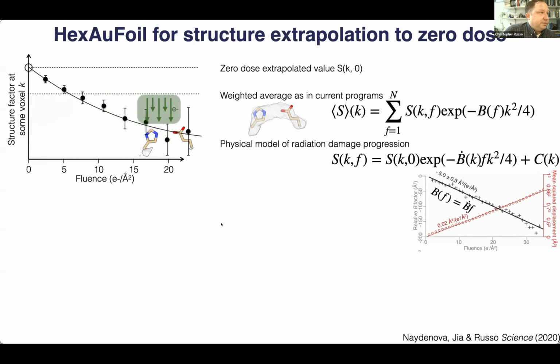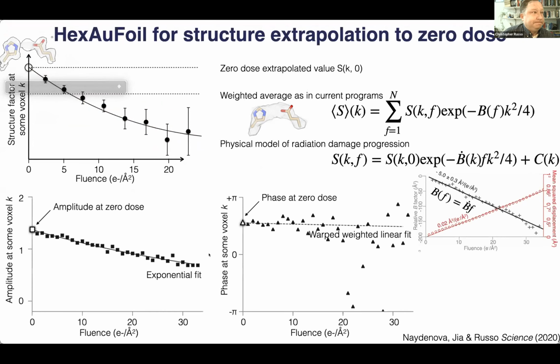So, this is just a little graphical illustration of that: you work your way back up the dose to the beginning, and then your final map is actually the best interpretation possible of what the molecule was like before you even turned on the electron beam. And this is what this actually looks like for some particular structure factors. This is an amplitude fit and a phase fit. And so this is what actually goes into the final map that you go and build your model into.